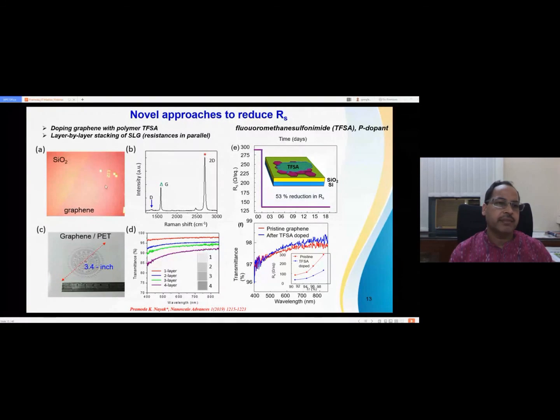So this is the typical graphene on the silicon oxide substrate. And unlike ITO, graphene is flexible. We have also prepared a 3.4 inch graphene film. It was transferred onto a flexible PET substrate. It has been shown here. This was done at National Tsing Hua University, Taiwan, when I was there. So here you can see this is the 2D Raman spectra, the 2D to G ratio is more than 1.5. This confirms that it is single layer graphene. Here you can see the transmittance. You can see there is a color contrast in the transmittance. So 4-layer graphene is showing a lower value, around 85 to 87% transmittance.